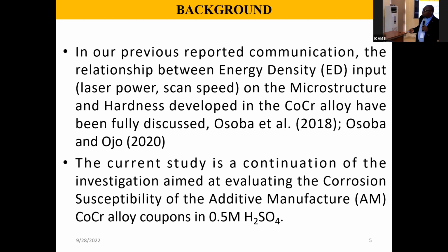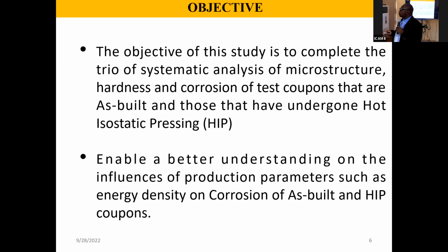So this is a continuation of the project. Some of the results of that project have been presented. In the previous publication, we looked at microstructure and mechanical properties. However, in this particular investigation, I'm concentrating on the corrosion stability of this alloy. While the other experiments were carried out in Canada, this particular one was analyzed here. So the objective is to complete the investigation of microstructure and corrosion behavior of this alloy, and that will help people better understand the effects of energy density on the corrosion parameters for this material.